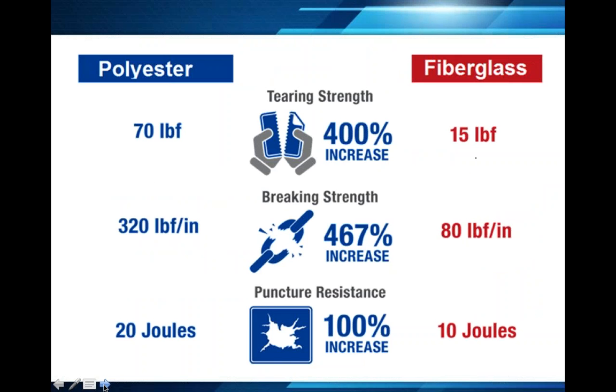When we look at the difference between a polyester and a fiberglass reinforcement, if it is mechanically attached, it has to be polyester. So we're really looking at a fully adhered application. So in that fully adhered application, that polyester would provide a 400% increase over the fiberglass in terms of tearing strength, fiberglass being kind of brittle. Also, it would have a huge breaking strength increase of 467%, and then a much better puncture resistance than the